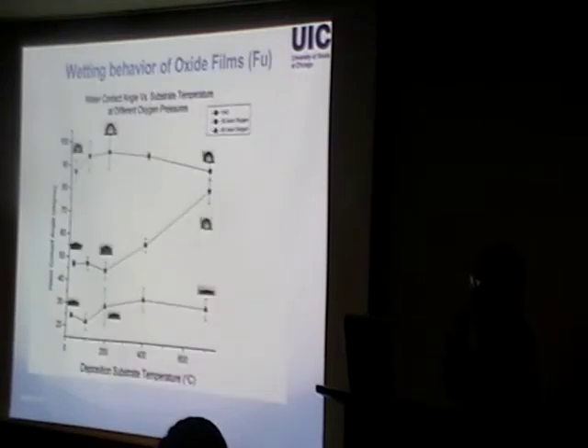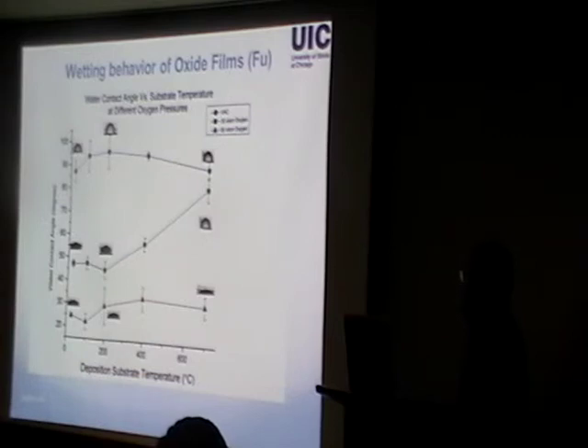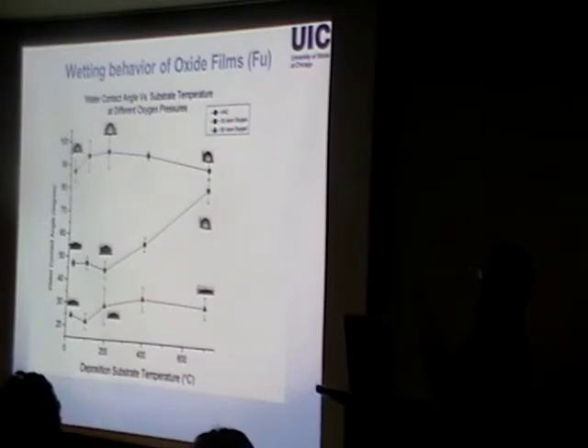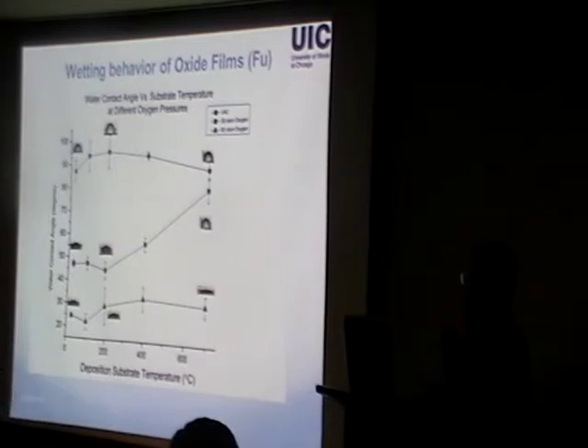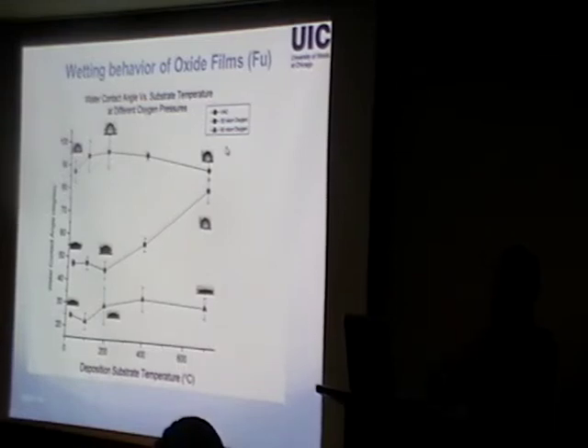And now I'm just going to show his recent results, and then that will be the end of the presentation. Okay, so what Fu did is he coated a silicon substrate with cerium oxide, which is the main rare earth oxide. He did this by depositing the sample at different temperatures. So you heat the silicon up to either 200 degrees C, 400 degrees C, or 600 degrees C, and you do that either in the presence of oxygen. Here the pressure in the vacuum chamber is 30 millitorr of oxygen or 50 millitorr of oxygen, and the sample that says vacuum, these dark circles, has no added oxygen.